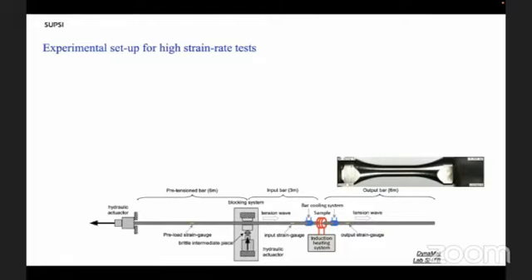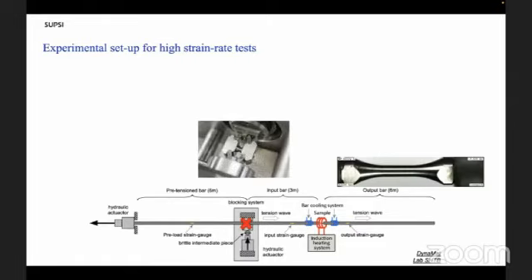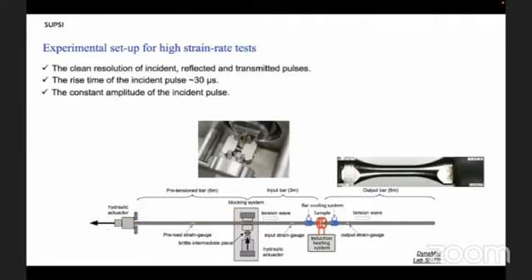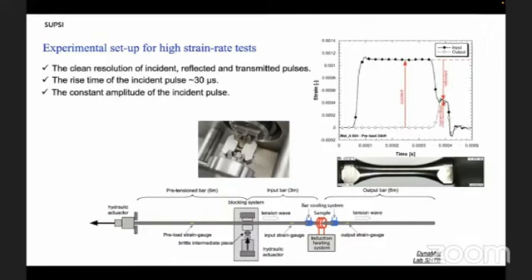By means of a hydraulic jack placed at the end of the bar, and thanks to the blocking device, the pretension bar is pulled, so we can store elastic energy and regulate the velocity in relation to the load amplitude. So we obtain very clean signals in terms of incident, reflected, and transmitted pulse, and the constancy of the incident pulse.